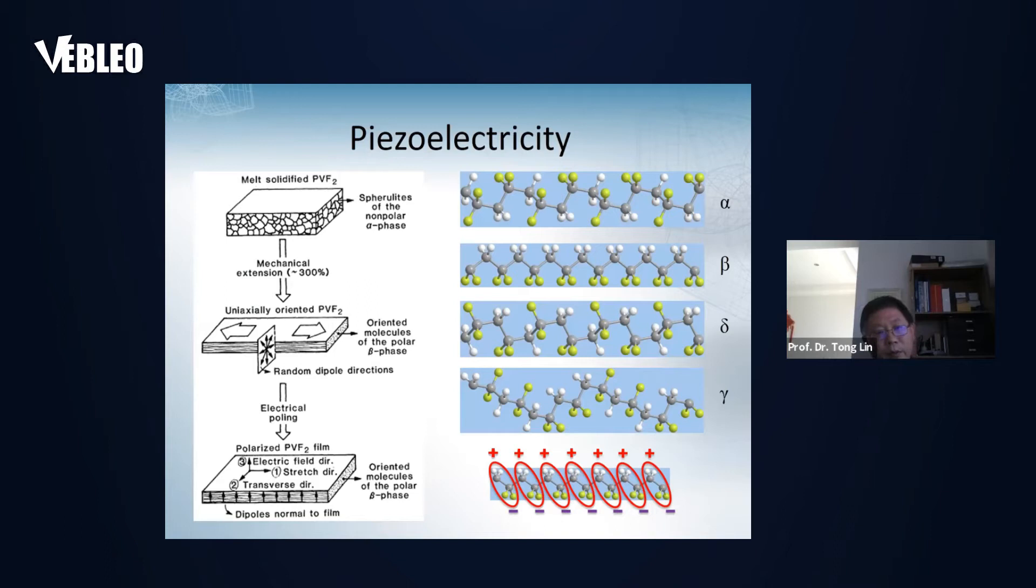I should point out that although PVDF is a piezoelectric material, its raw material doesn't contain piezoelectricity. To achieve this in the industry, people need to treat that material in different steps, including casting into a film and then stretching along a specific direction. After that, they still need to place it into a high-voltage electrical field for poling treatment.